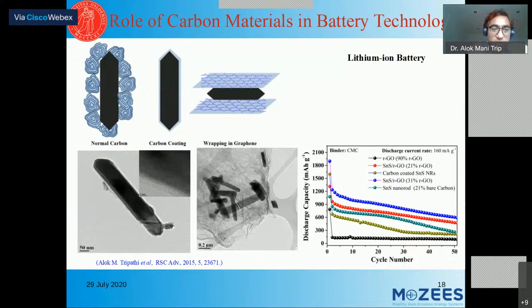So here is one of my research works. We have used three kinds of carbon. Basically some spherical carbon, then we coated the particles with carbon, and then we have graphene, which is a 2-dimensional sheet. Here you can see the TEM image. The particle is coated with carbon, this is a 5 nanometer carbon coating on the surface. And then there is the graphene surface supported with the tin particles.